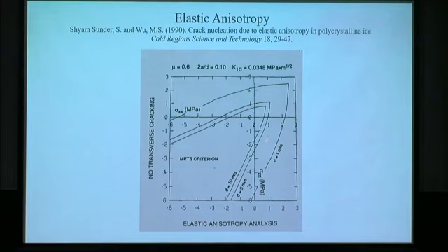If you have a smaller grain size, d equal to 1 millimeter, the uniaxial compressive stress is higher, maybe something like minus 5.5. So this is the tension region. If you have biaxial tension, this region is something like tension-compression, and this is biaxial compression, and so on. So we did some analysis on the dependence of crack nucleation on the multi-axiality of your loading. All this is pretty straightforward because we use the concept of linear elastic fracture mechanics, LEFM.